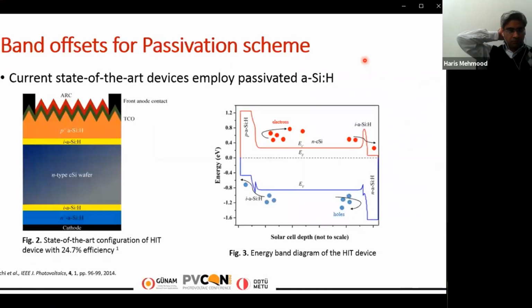For any solar cell device, the band diagram is a very important figure to determine the charge transportation characteristics of the device. For a traditional heterojunction with intrinsic thin film solar cell, HIT device, the energy band diagram tells us that the energy barrier height is approximately 1.2 electron volt against the minority carrier electrons at the front interface. Similarly, the energy barrier height is approximately 0.4 electron volt against the majority carrier holes. So these band offsets promote the transportation of specific charge carriers. For example, the 1.2 electron volt conduction band offset at the top side will try to repel the minority carrier electrons away from the anodal interface. And the low barrier at the anode side for the holes will promote the transportation of the majority charge carriers towards the anode contact.